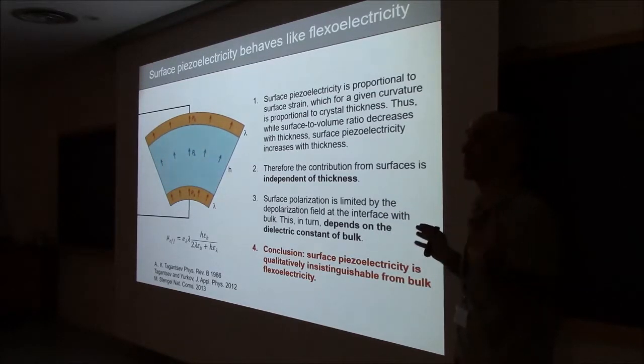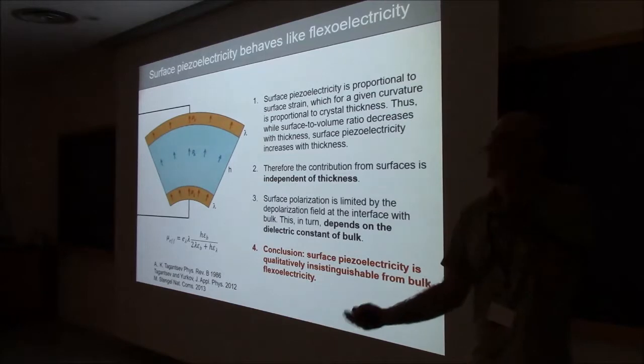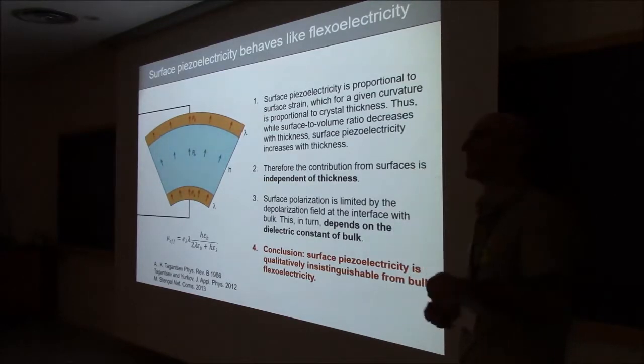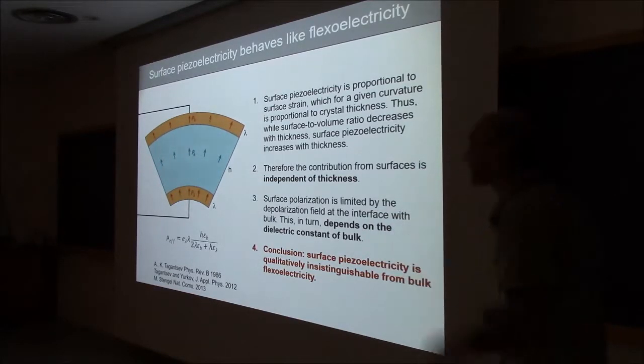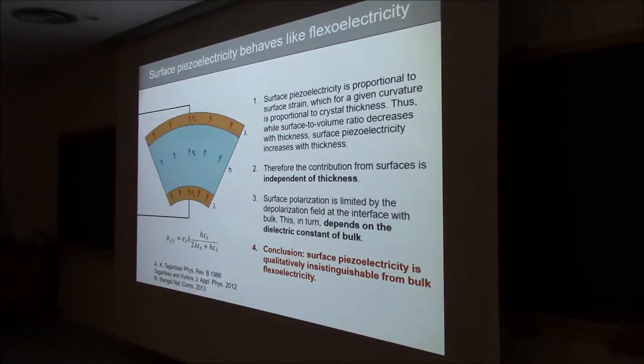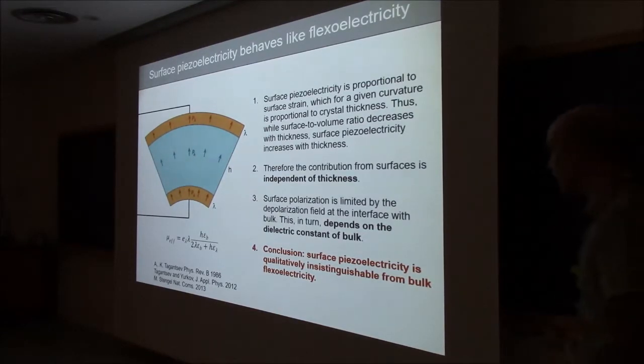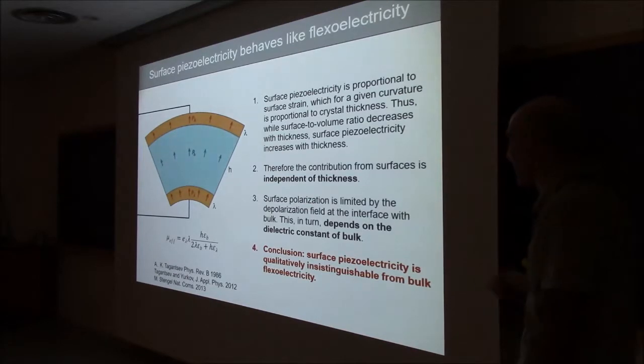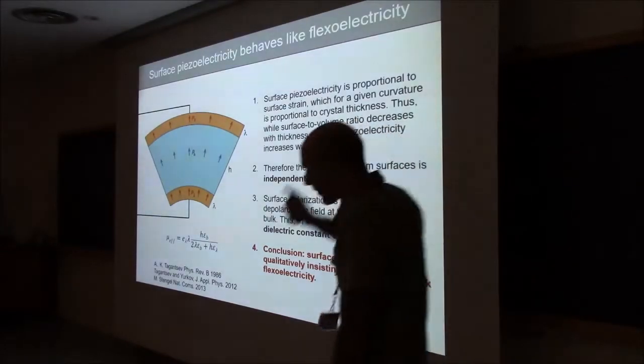I found that absolutely outrageous. You have a 1 millimeter thick crystal, you change just the last atom, and you change completely the sign of the polarization. I didn't believe him. Experimentally, I still haven't managed to prove whether he's right or not. But now I understand the physics, and I think the physics is solid. In fact, physics coming from Max, chances are that it's always going to be solid. That's a different thing. Okay, so it's independent of thickness.